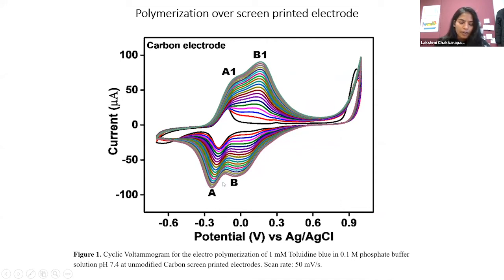So when we use the polymerization method, the toluidine blue monomer starts to create a monomer radical, and then this radical binds together one by one, and then finally we get the polymer form because of the applied potential and the current. And A and A1 represent the monomer of toluidine blue, and B and B1 represent the polymer peak. The first cycle doesn't show any polymer response because initially we can't get the polymer film. And then at the 30th cycle, you could see the B1 shows a higher current response at 0.0 volt.